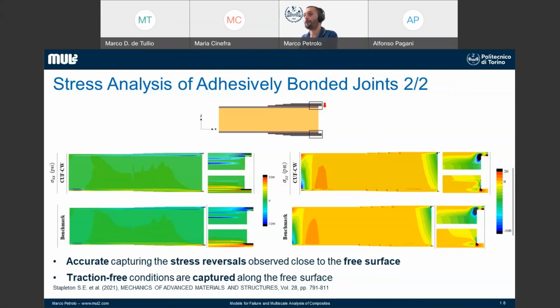First of all, all 6 components of stress become important. So you need both the in-plane and out-of-plane stress fields in order to have good accuracy for these models. And then you have very high gradients in the area of the constraints. In this area, you can see a very high variation of stress in a small area. And to do so, you either use 3D finite elements or refined structural models such as those that we have available in our code.